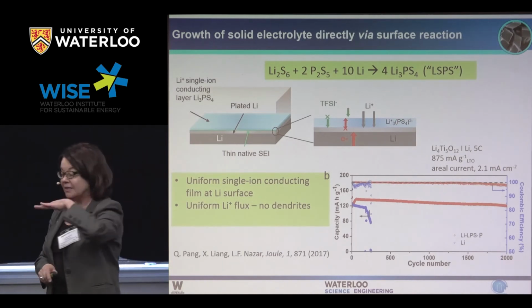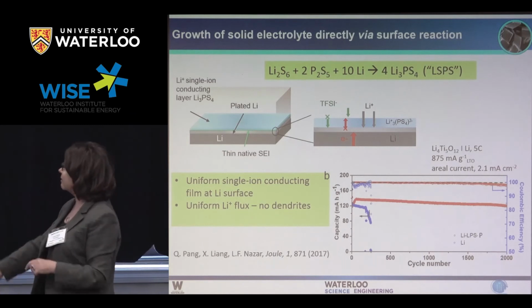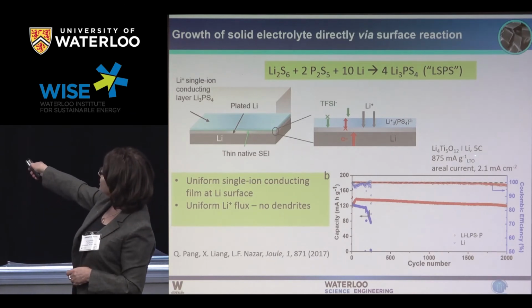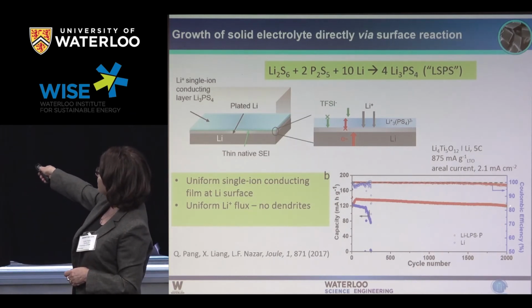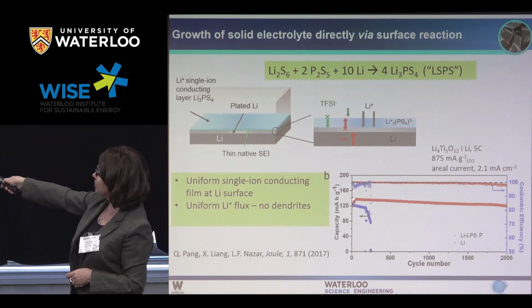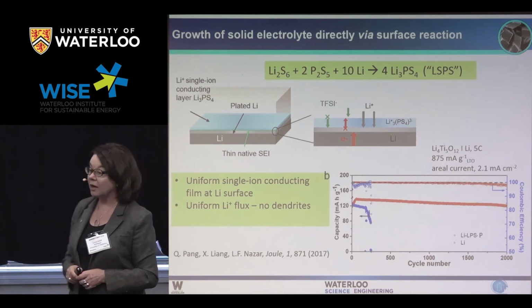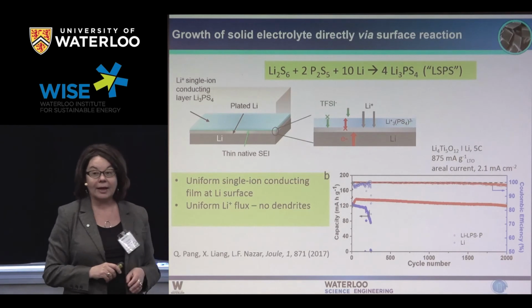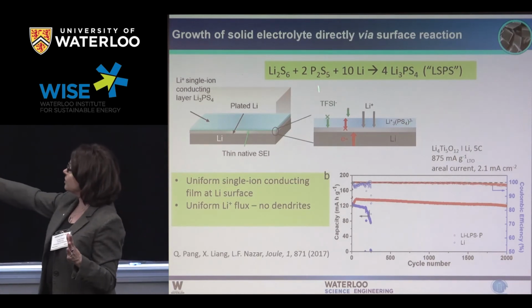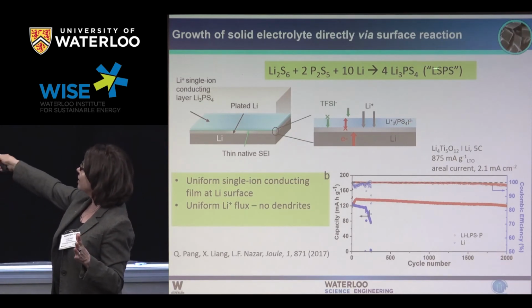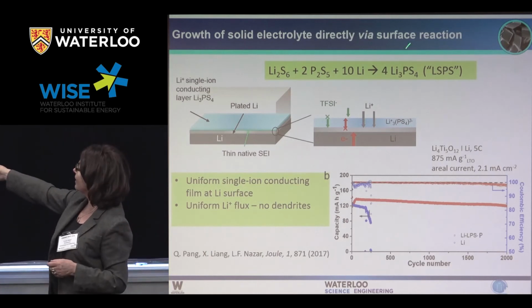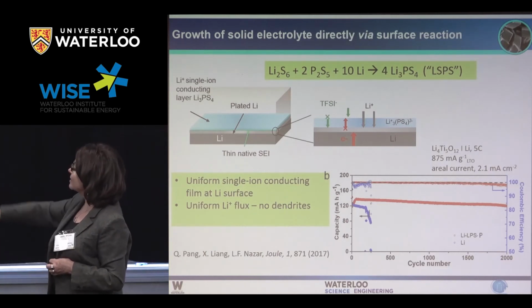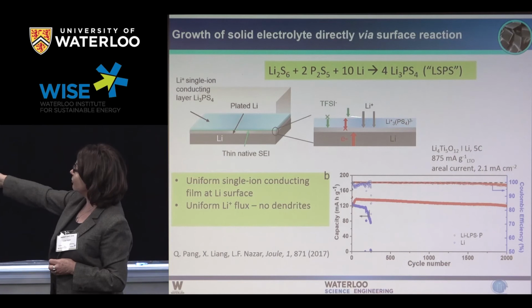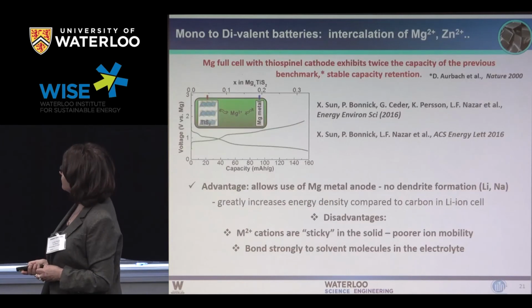And we have a nice, simple, flat, homogeneous lithium flux. And that has allowed us to cycle a lithium cell for 2,000 cycles, as you can see, whereas the unprotected cell dies within a couple of hundred. And again, it's a simple, scalable approach where we just use simple chemicals treated with lithium. I mean, it's not really that simple, but anyway, to create this thin, homogeneous film that allows the lithium ions to pass.